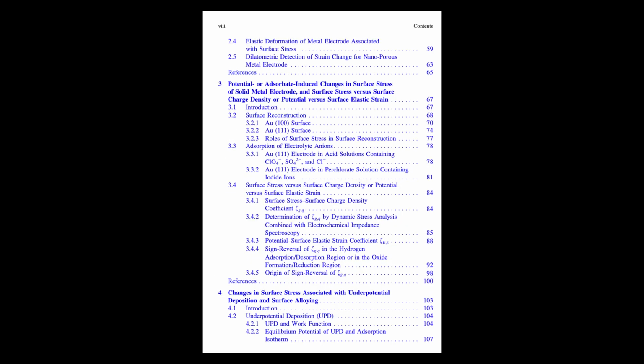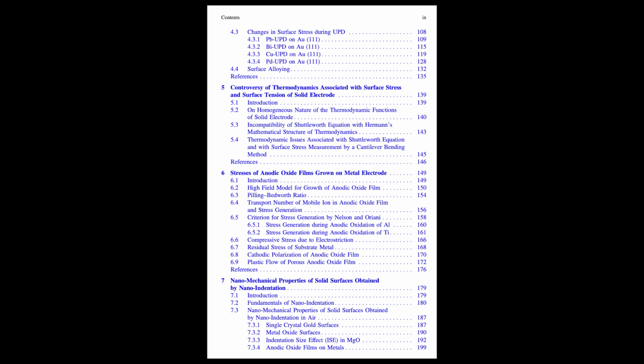What happens if you try depositing, say, bismuth on gold instead? Does it behave the same way? Good question. Bismuth by UPD on gold 111 is different. Unlike lead, bismuth doesn't really form surface alloys readily with gold. Instead, it forms its own distinct structural phases on the surface. And the stress changes reveal something called uniaxial electrocompressive stress. Uniaxial, meaning? Meaning that compression is mainly oriented in one particular direction along the surface, not equally in all directions like the lead case. So different metals, even as these ultra-thin layers, leave their own unique mechanical fingerprint based on how they interact and arrange themselves.